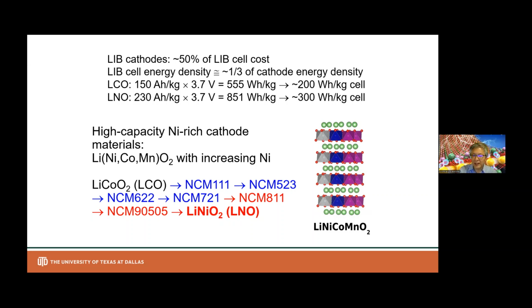But if you take half of them, which is 140 milliampere hour per gram, this material becomes unstable. If you remove these lithium ions, the cobalt tends to move and change phase. So over the last 3 decades, there's been a gradual evolution of the cathode material, by increasing the content of the nickel and adding some manganese. The manganese stabilizes the structure, and cobalt still maintains this layered oxide, which is the initial lithium cobalt oxide.